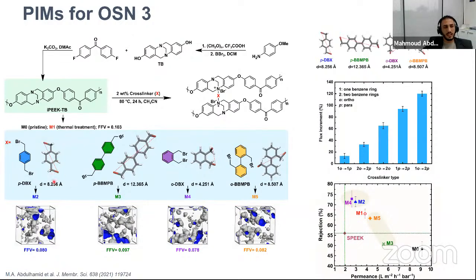So we thought of taking 4 cross-linkers. These two are para substituents, so this and this are para. This one is 1 ring, this is 2 ring. These are ortho substituents. So here we are changing the stereochemistry between para and ortho, and also 1 ring and 2 rings. By calculating the distance between the functional groups, we can see we have different ranges in terms of size. After testing and analyzing this material, we found that the cross-linker plays a very important role in determining the performance.